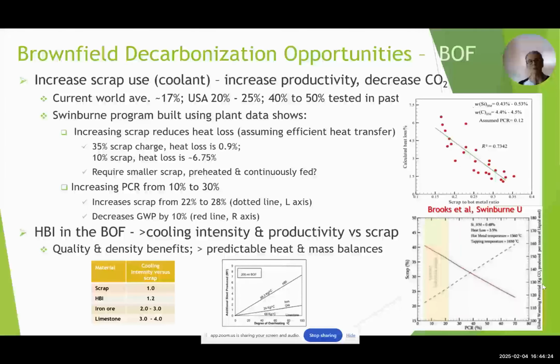Increasing PCR on the bottom from 10 to 30%, you can see an increase in scrap from 22 to 28% on the dotted line, and global warming potential drops by 10%. These two charts basically show HBI and the BOF as having greater cooling intensity and productivity than you have with scrap.